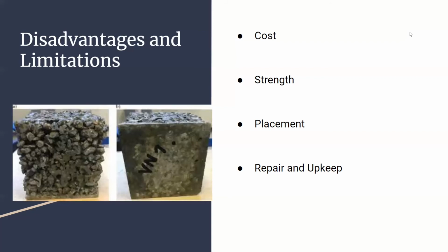Repairing the concrete can be quite difficult since most road repair substances that are used also act as sealants, which conflicts with the purpose of using pervious concrete in the first place. When used on high-speed roads, large aggregates tend to break off, which may then be launched into people's windshields, creating a safety hazard and could result in lawsuits. It is also quite possible the pores of the concrete may become clogged by leaves or soot, and it would then need to be cleaned with a street sweeper or a power washer.